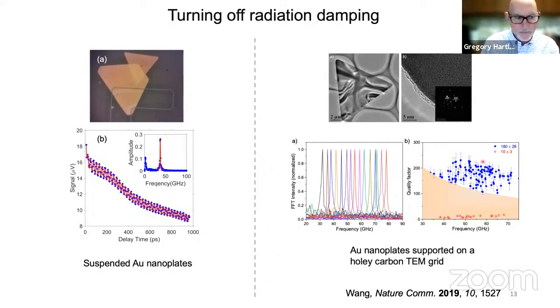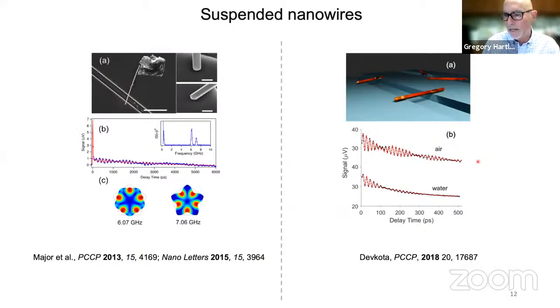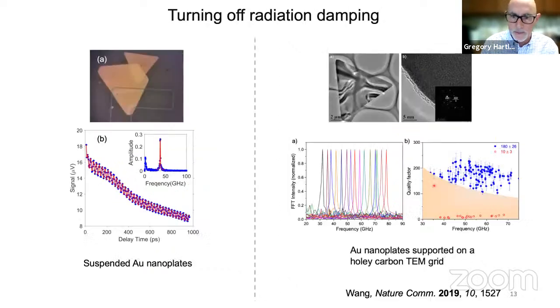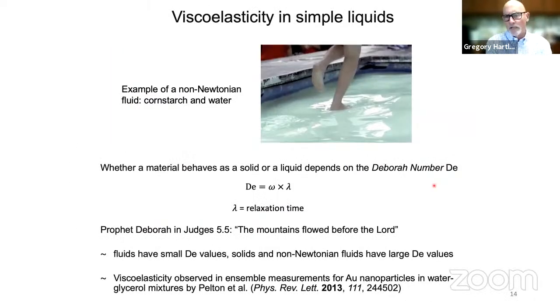Okay, so the first thing to talk about is the interaction with liquids. And just skipping back, what we do in these experiments is that we measure the lifetimes or quality factors in air. We add a liquid and we come back and measure the lifetimes and quality factors of the same nanostructure in the liquid. And the difference between those two measurements tells us about the liquid. And the reason to do this, which was motivated by my collaborator in Australia, John Sader, who's worked with almost anyone who does stuff with vibrations and nanostructures, was to try and explore viscoelasticity.